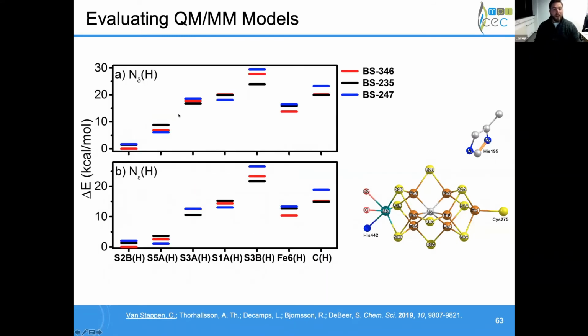If we also look at the actual energy profiles, what are more favorable models relative to one another, we also see the S2B and the S5A are significantly more favorable than basically anything else that we tried out here. And so between this decent match with our experimental data and this energetic data, it seems like it's a really good indicator that one of these sites is responsible for, or is the site of protonation in E1.